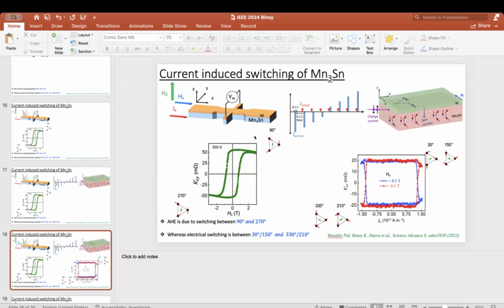Whereas in non-magnetic material like copper or others, there will be only the ordinary Hall effect. But there are some materials like non-collinear antiferromagnets, whose moment is very small, like 10 to the power -3 or typically of the order of mu B. And then we observe a large anomalous Hall effect. So there is no correlation between the magnetization and the anomalous Hall effect. You can't correlate. If you compare, let's say, iron, that magnetization, let's say 1000 emu per cc, corresponds to this amount of anomalous Hall effect. If you do a similar comparison with this non-collinear antiferromagnet, that will not be satisfied. That's why it doesn't scale, basically. Does it answer your question?